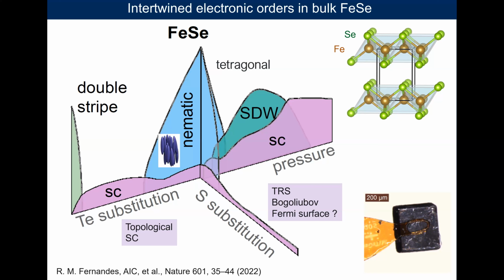Well, there is no neutron diffraction, but it's believed to be collinear antiferromagnetism. Indeed, that's a proposal. However, there is no direct evidence from neutron diffraction because experiments are not available. But here, it seems that the nematic is decoupled from this magnetism. Still, on general grounds, one would expect that there is a precursor nematic transition. Again, it could be unrelated to the nematicity in this zero pressure region, right? But that's right. Can you rule out that there is maybe a 1 Kelvin nematic region above the SDW as well?